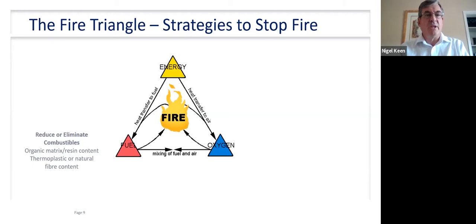So we can do several things when we're building our composites. We can reduce or eliminate anything that's combustible. So we can reduce the resin content, if it's an organic resin. We can get rid of any thermoplastic fibers that might be flammable. We can perhaps remove natural fibers or something else that's flammable. So we can get rid of the combustibles and perhaps substitute them with other things. So high glass contents, inorganic fillers, and keep the combustibles to an absolute minimum.